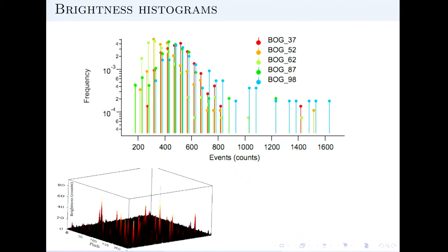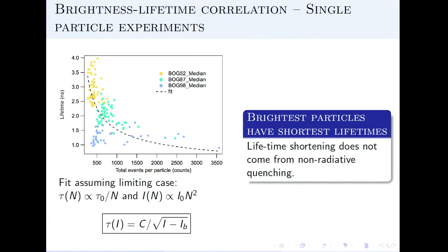What's really interesting is when we start to hit the 100 chromophore per particle threshold, we have very, very bright single particles, and they stand out. So those are worth studying. We don't have the time resolution, actually, to measure exactly what the burst time is for those particles. But we have asked ourselves, is there a correlation between intensity and lifetime? Because that's what the superradiance emission would predict.